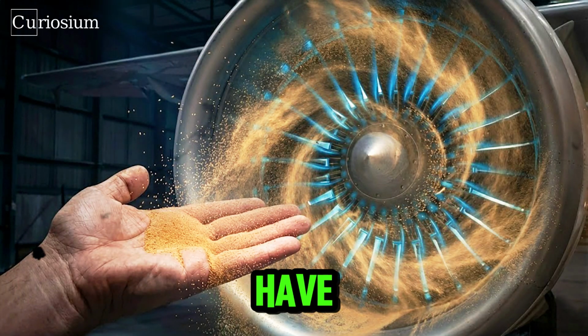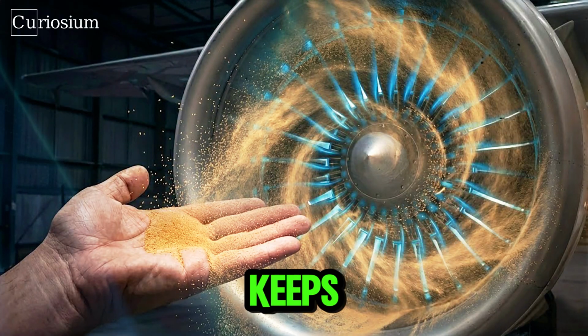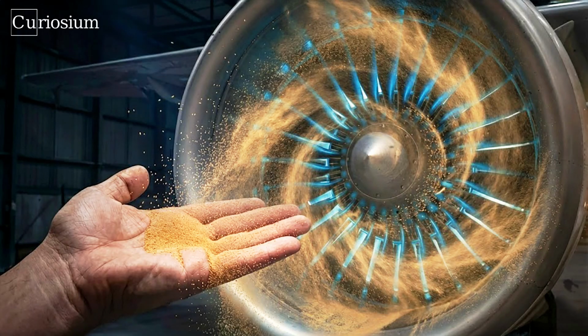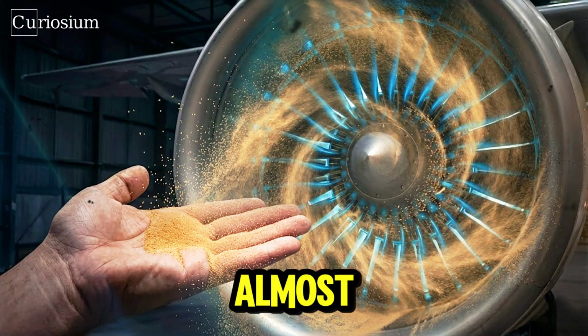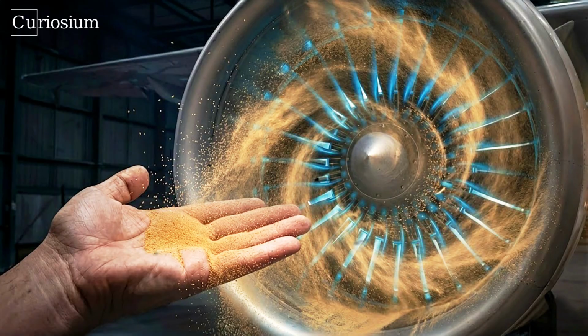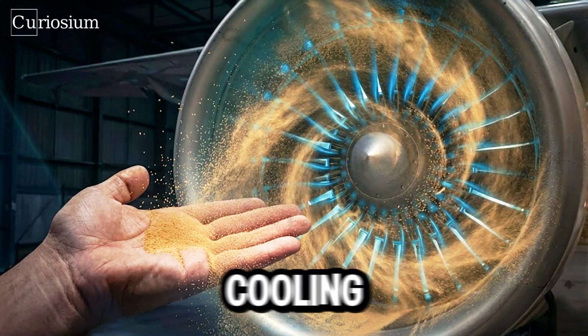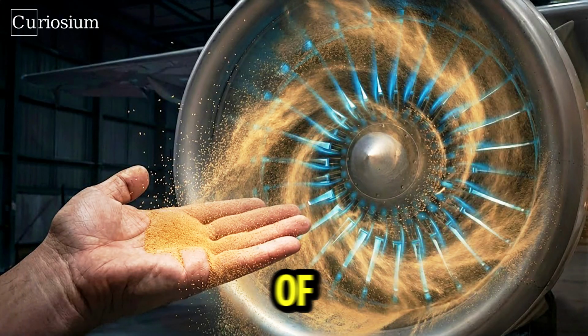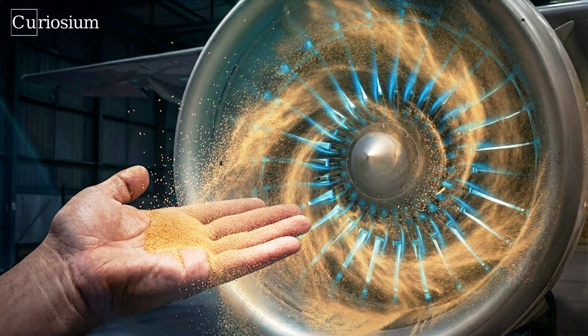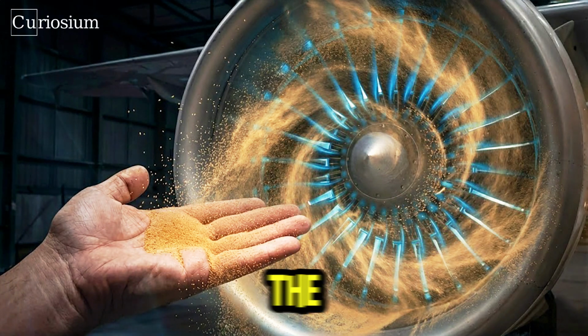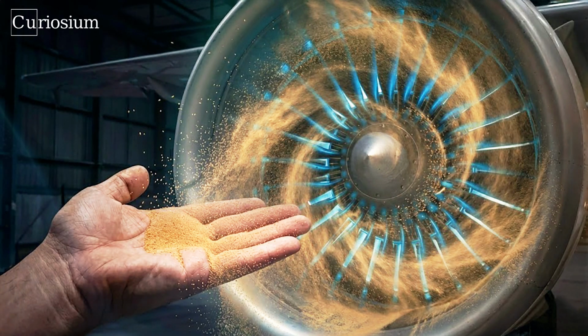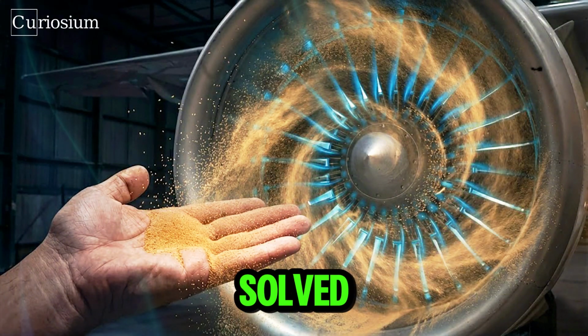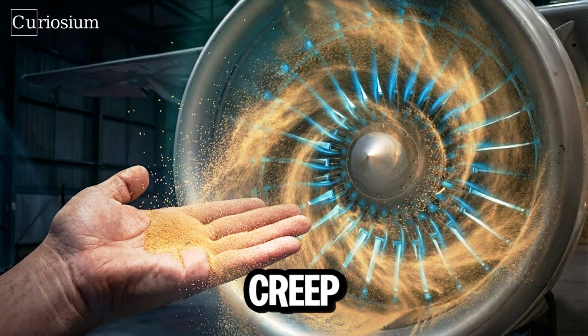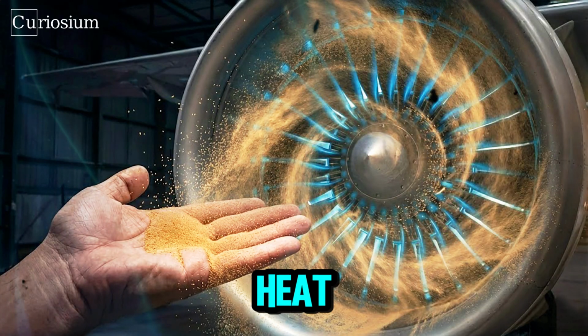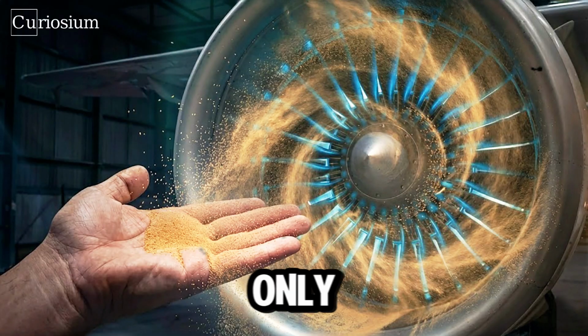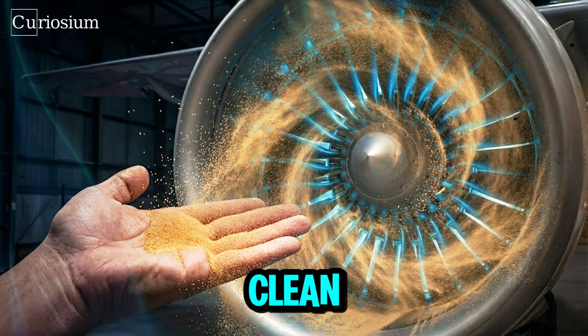So now we have a superalloy that keeps much of its strength at high temperature. A single crystal blade with almost no weak grain boundaries, internal cooling passages and film cooling that create an invisible layer of protective air, a ceramic jacket that shields the metal from the hottest gas. At this point, it sounds like we have solved the problem. Strength, creep, oxidation, heat, all handled. If only the atmosphere were perfectly clean.